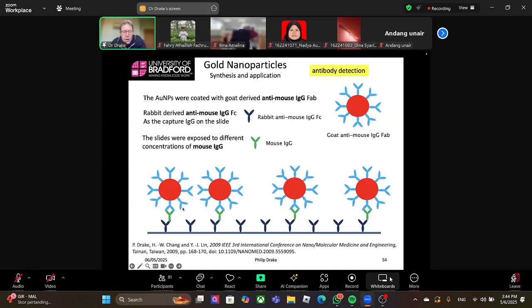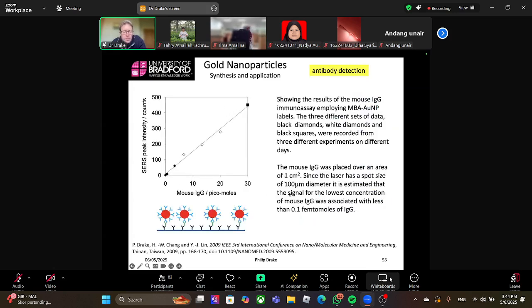We can wash off anything that's not bound. We then take the Raman laser and shine it on the surface. These nanoparticles will scatter the light and give us our signal. And you get a very nice linear dependence on concentration of mouse IgG in the picomolar region. So we can actually achieve femtomole detection. So we can detect a very, very small amount of IgG using laser systems.